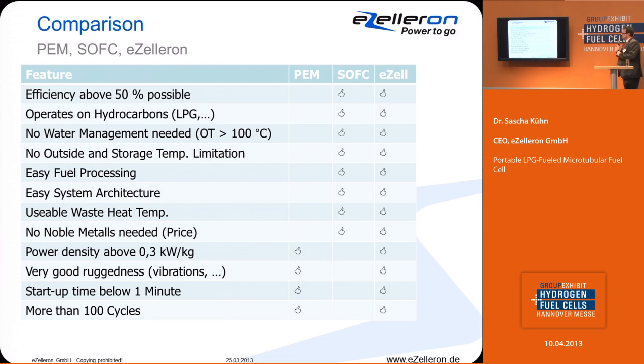So compared to other fuel cell technologies, we think that eZelleron's technology fits to all the advantages of a solid oxide fuel cell, like high efficiency, operation on hydrocarbons, not needed water management, and so on. And also has all the advantages of a PEM system, which means very high power densities above 0.3 kilowatt per kilogram, very good ruggedness against vibrations, and startup times below 1 minute, and more than 100 cycles, which you cannot do with a typical solid oxide fuel cell system.